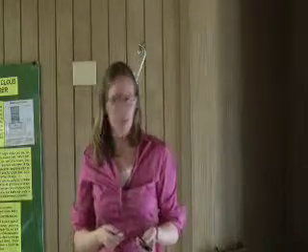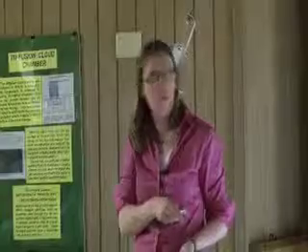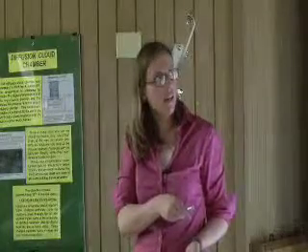We can also use time-resolved techniques with X-ray sources for the imaging, and this allows us to have better spatial resolution in our structures. So if we have a little strip line here and our little magnetic sample sitting on top of this waveguide here, we put a current pulse through that wire. That gives us a little magnetic field around the wire, and that excites the sample.